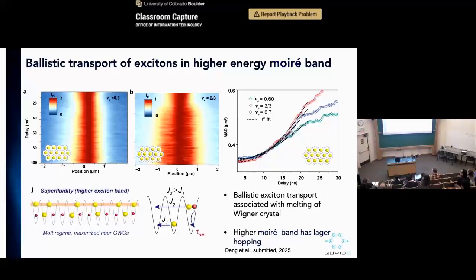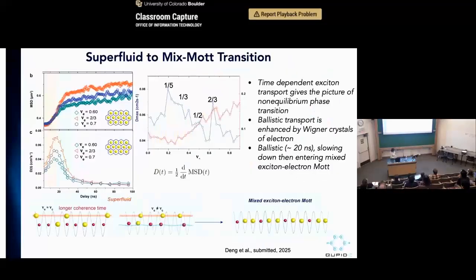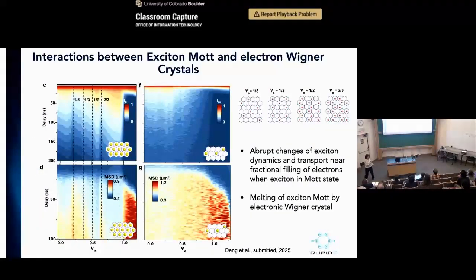Oh, well, maybe I'll ask one. Okay. Yeah. So I just flood excitons everywhere. Excitons are everywhere, and the charges are at fractional filling. What's also interesting is that the correlation of excitons really matters. If I go to a very low density of excitons but the same charge, my charge still forms a Wigner crystal at 2/3 filling. It doesn't change. But if I only have a diluted exciton, the excitons can freely hop around, so the interaction is also not as strong. So in the low density exciton limit, you don't see these abrupt changes at critical filling of charges.